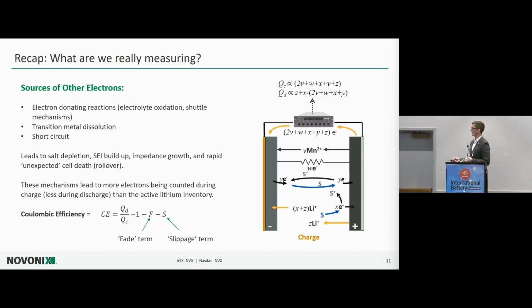And one really important thing to highlight on this slide is that within the very simple boundaries of each of these mechanisms shown, there's no direct loss of lithium inventory. I'm not showing any capacity fade in any of these mechanisms. They may trigger capacity fade later, but within these slippage-based mechanisms, there's no lost capacity. So you can have a cell with lots of these mechanisms happening, and eventually these may lead to salt depletion, impedance growth, and sometimes this is the main contributor to your kneeing, your rollover failure. And so if we can measure and quantify these types of mechanisms, it can be really useful for doing really rapid development, identifying things really early that are going to matter way out in time that we can't actually see with traditional metrics like capacity fade.